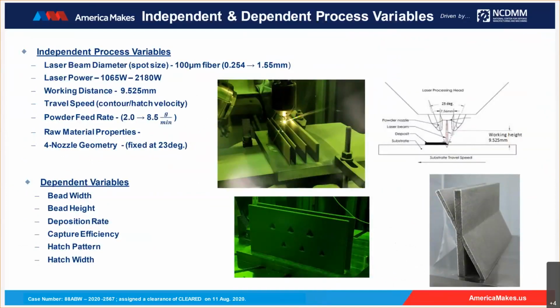From the equipment capabilities and process control parameters, you can see that there are 7 primary independent process variables: the laser beam or spot size, laser power, working distance, travel speed, powder feed rate, raw material set, and the nozzle. These give rise to several dependent variables that are specific to their settings, which result in the actual build results that you would obtain.